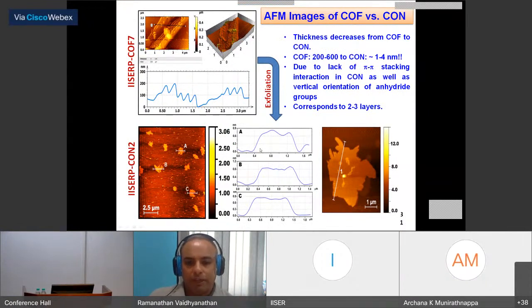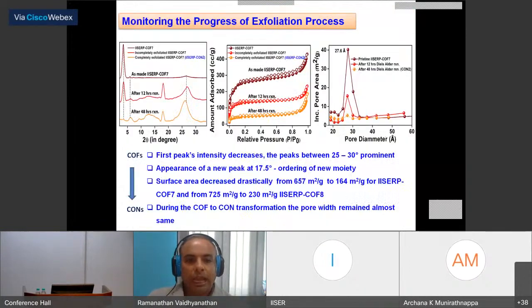From the height profiles, you can see that a COF with a thickness of about 200 to 600 nanometers goes down to as thin as 1 to 4 nanometer, which corresponds to only 2 to 3 layers of the COF in the exfoliated form. And this is easily something that will accommodate only a few maleic anhydride unit thick layers. And this is something we developed in our group, where we can track this exfoliation also with powder X-ray diffraction.